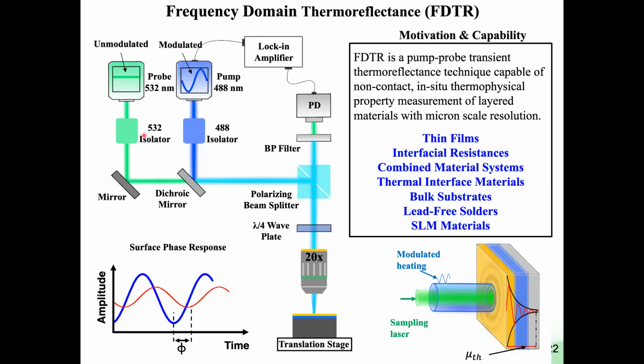So next we wanted to measure the thermal properties of these printed materials. To do that, we use a technique that we have in our lab called frequency domain thermoreflectance. And this is a pump probe laser technique. Basically, we use a modulated laser, this blue laser, to hit our sample. So this is a microscope objective, and it gets focused to about a 3 micron spot. We have several objectives, but the one that we use now gets focused to a 3 micron spot. And that's basically periodically heating that little point.